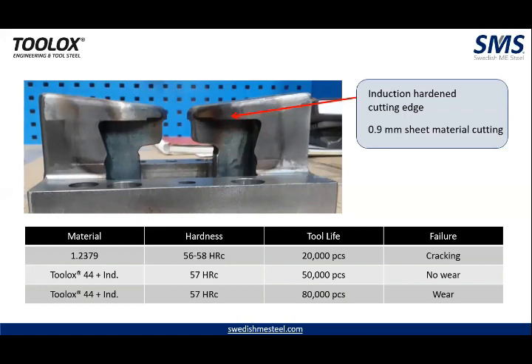So as you can see in this particular slide, the initial metal used was D2, but at 20,000 pieces for this particular material, the failure mode being cracking. It was on 0.9 sheet metal cutting. So then Toolox 44 along with induction hardening was roped in. Up to 50,000 pieces, no wear. Even up to 80,000 pieces, it went on well. But at 80,000 pieces, there was a failure mode, but it was only wear, not cracking.